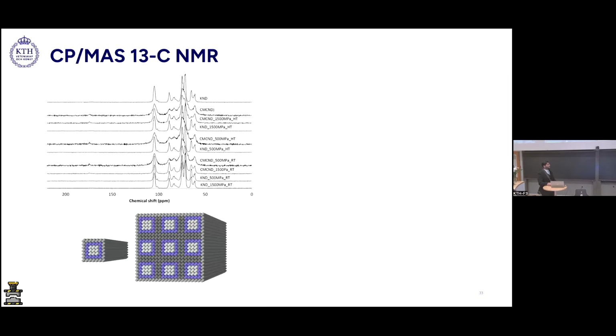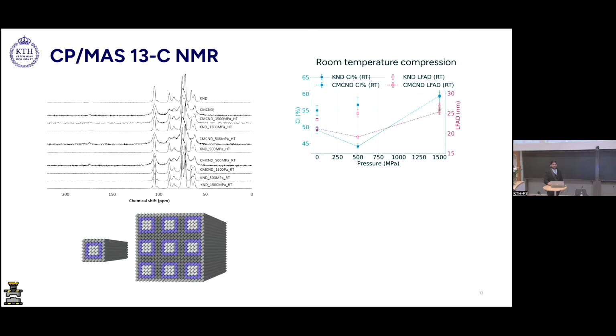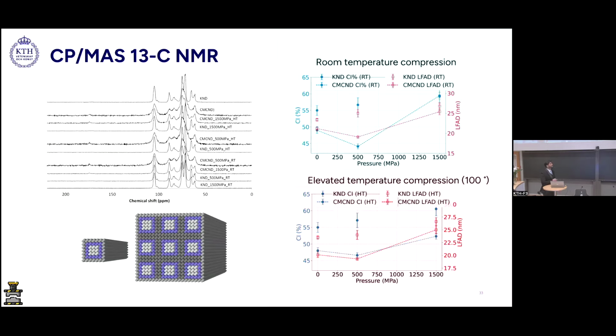To support this data, we also did solid state NMR, which was done at Rice. In solid state NMR, we pretty much saw similar results. For Kraft pulp at room temperature as well as elevated temperature, we saw an increase in the crystallinity. In carboxymethylated pulp, we saw a little decrease in the crystallinity at 500 megapascals, but then it went up again at 1500 megapascals.